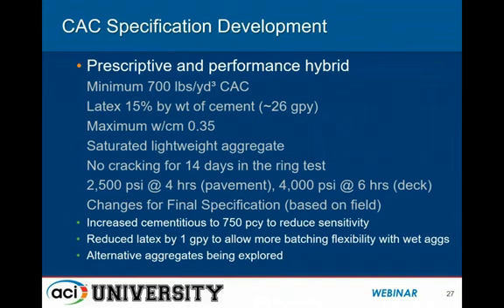So this is what we ultimately wound up with. It was a hybrid specification. It wasn't purely performance-based. We wound up using the saturated lightweight and no cracking in the ring test for at least 14 days. That was our target. And then finally, we upped the final cementitious materials content to address some of the sensitivity that we saw with strength. So I think using the latex in conjunction with the CAC allowed us to get the scaling and the freeze-thaw durability, and then using the saturated lightweight for internal curing gave us the crack resistance.